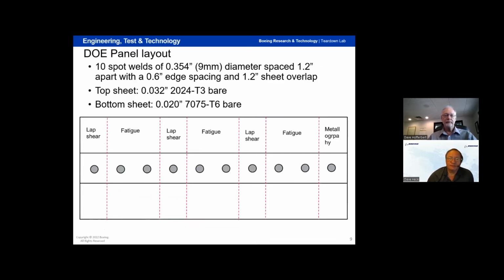Okay, there you go. So as Dave was mentioning, these are 7075 and 2024, but very thin. You have 52 thousandths thick for the total thickness where you're putting the weld or the rivet. So these were done with a 9mm or 0.354 inch diameter tool that was spaced 1.2 inches apart, and with an edge distance of 0.6.